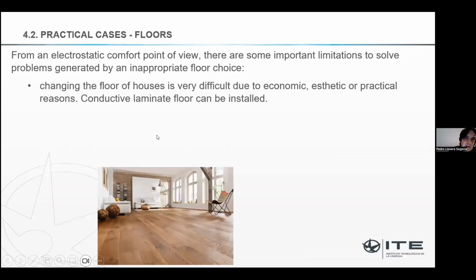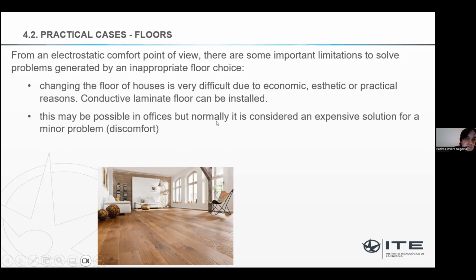You can also put some conductive laminate floor that exists and it works. We've measured it and it works. We tested in our lab conductive laminate floor and it works. But it's expensive again. At least it's a nice floor. But if you already spend a lot of money on a very nice floor, which is not anti-static, and then you have to spend money again on laminate floor, it can be a problem. Normally, it's considered an expensive solution for a minor problem. So it's difficult to find this solution once the floor has been installed.